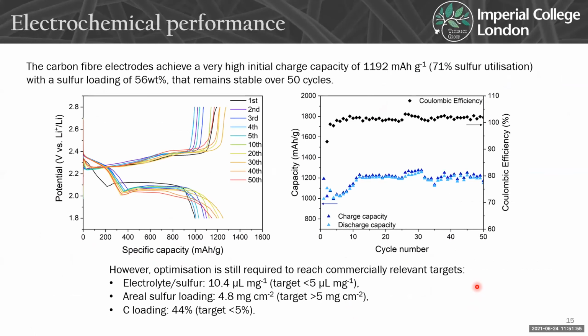So then when we look at the galvanostatic cycling, we can see that we managed to achieve a very high initial capacity of around 1,200 milliamp hours per gram, and that's equivalent to 71% sulfur utilization. So we're not accessing fully all of the sulfur, but this is still reasonably high for this material, and it remains quite stable over 50 cycles. But obviously this is quite preliminary work at the moment, so there's still lots of optimization to be done for this system.